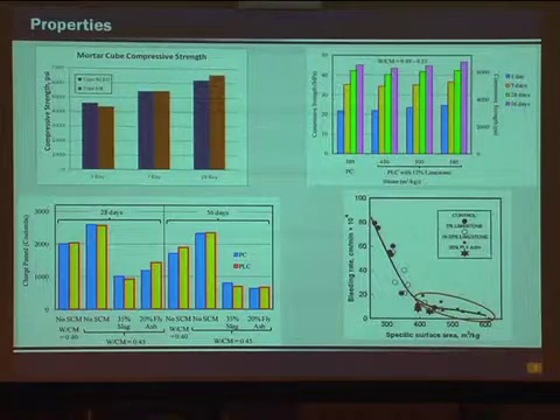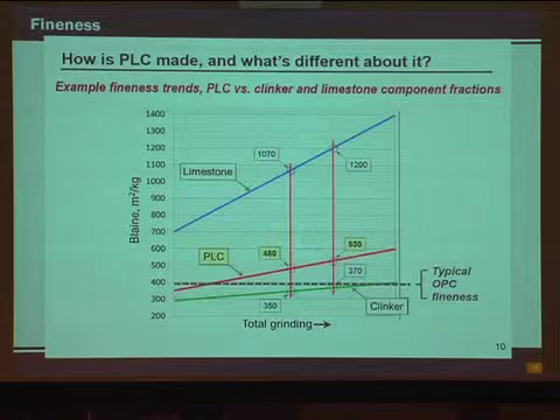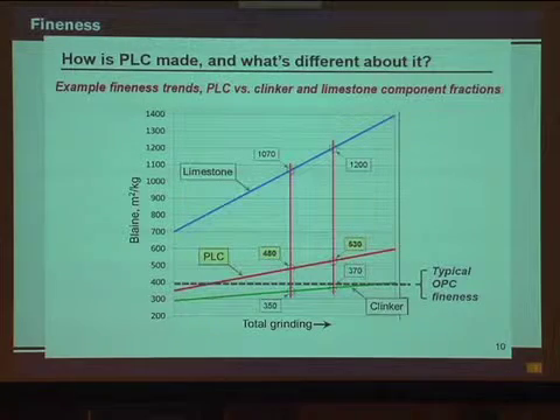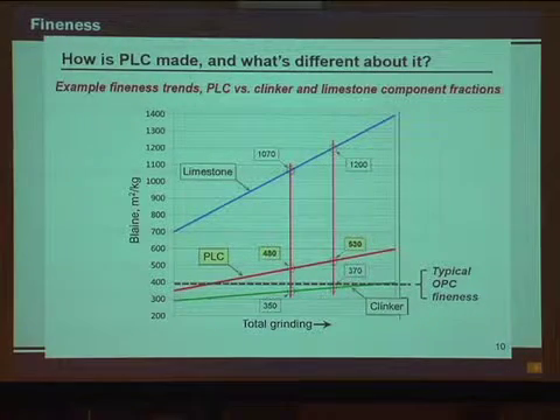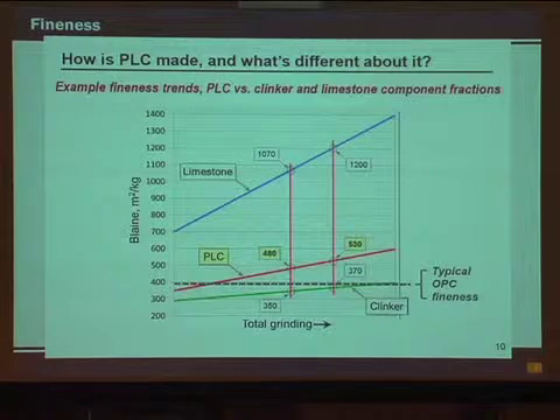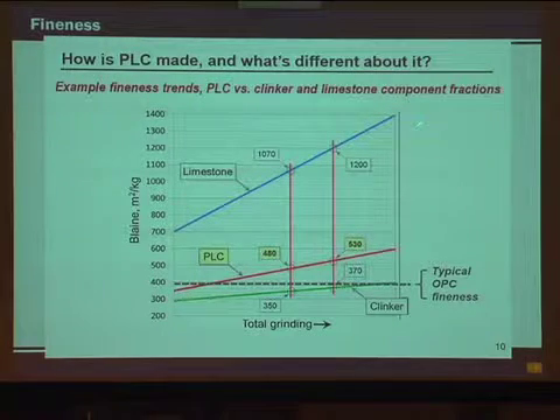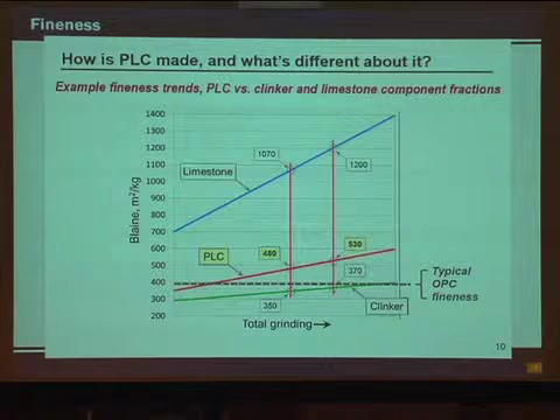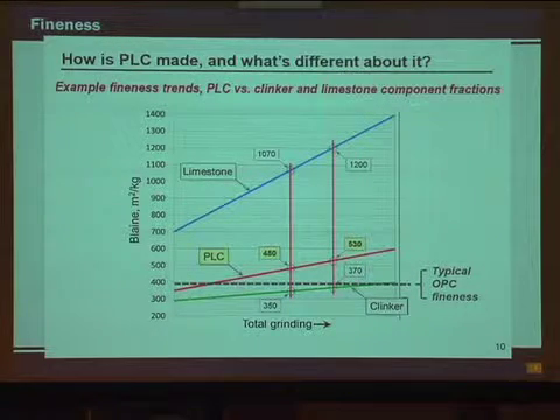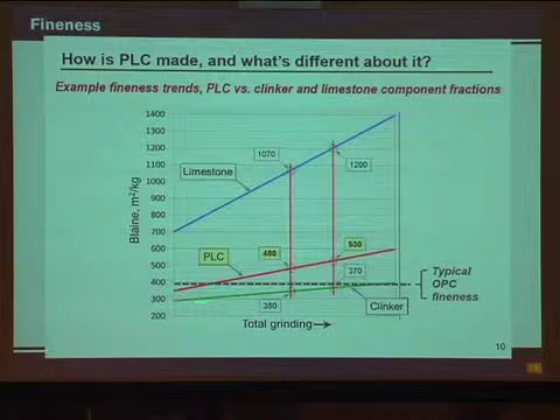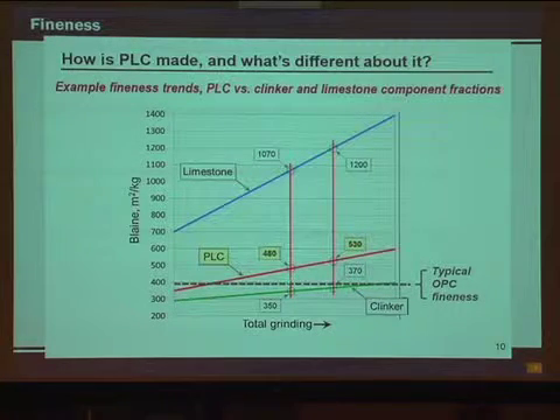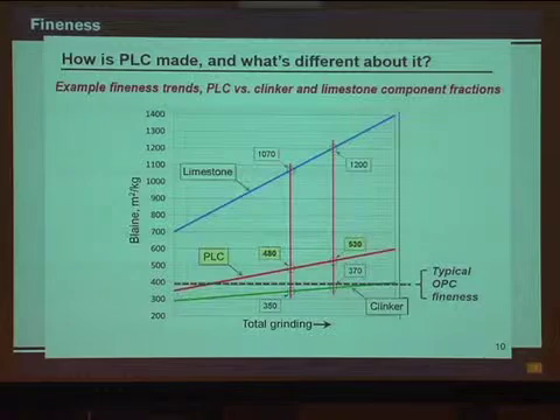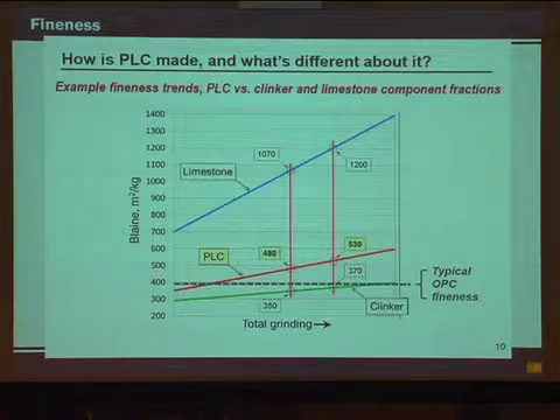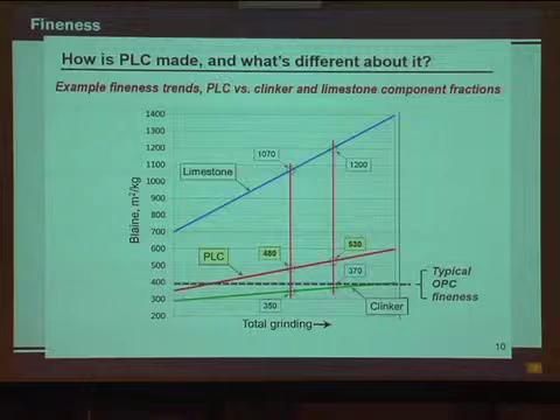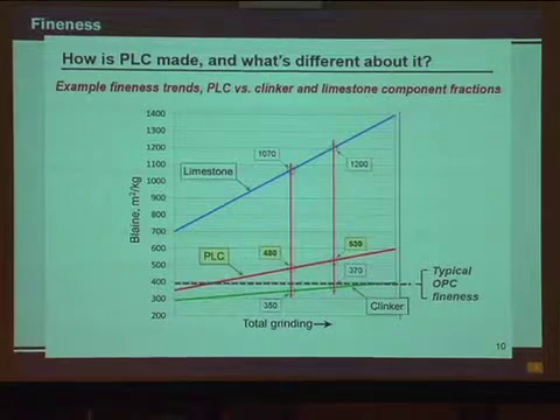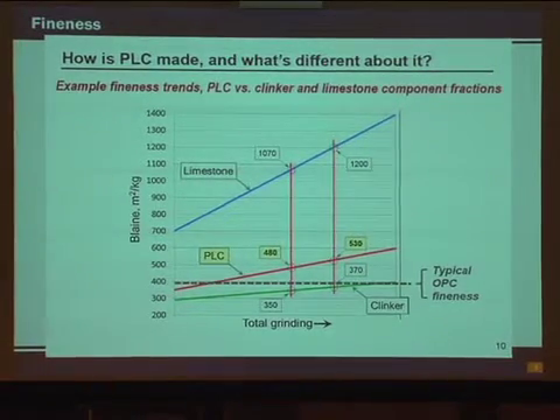So, just a little bit on fineness. When you intergrind that limestone in the mill, since it's softer than clinker, it grinds a lot finer. If you look at the Blaine of just the limestone, you're up here in the thousands. When you look at the clinker, you're down here. And the blend of the two puts you on the red line here. So it may seem that you're getting finer, but really it's a false indication, because the limestone is ground so much finer than the clinker.